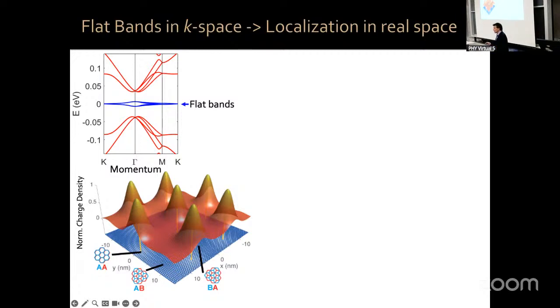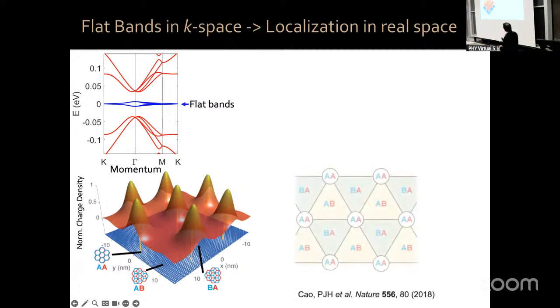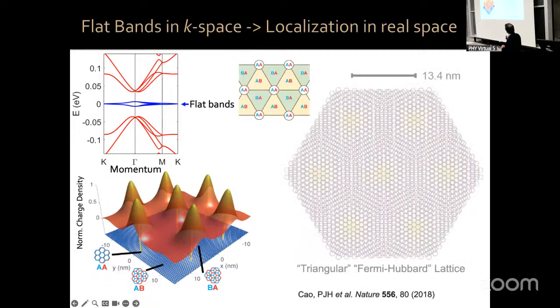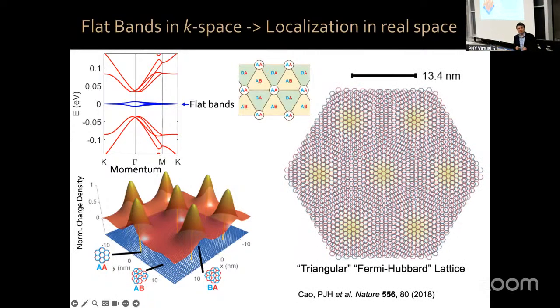So schematically, magic angle twisted bilayer graphene looks like this: there are regions of AA stacking where electrons like to be, and regions of AB and BA stacking where electrons do not like to be. In a slightly more realistic schematic, the AA stacking regions are shaded in yellow where electrons like to be, and the AB and BA stacking regions are where electrons do not like to be.